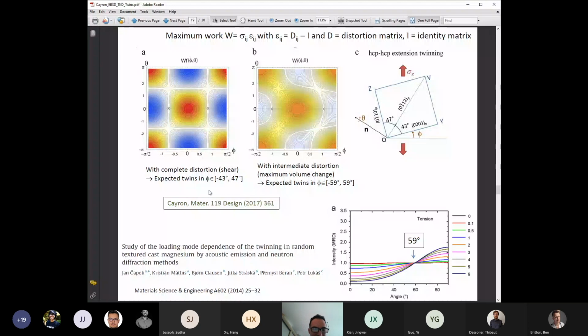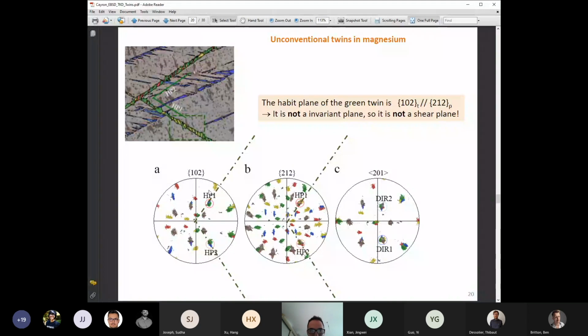And what is nice is that with a simple shear, you predict that you form twins between minus 43 and 47 degrees. But with this hard sphere model, you predict that you can form twins between minus 59 and plus 59. And I don't know if it's by chance, but there is an experimental study that reports exactly this angle of 59 degrees. Okay, I know that I was too long, so I will skip this part.